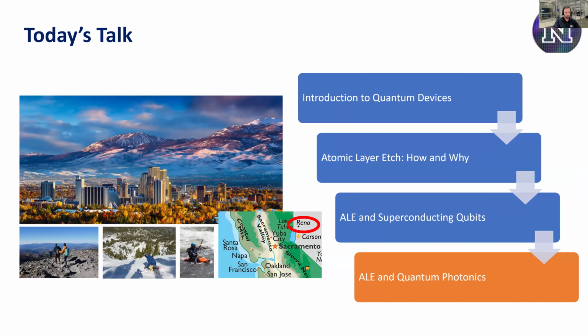The other thing you'll need is to detect the photons at the end, and that's done using superconducting nanowire single photon detectors. These are pretty interesting. You make really thin, like 5 to 10 nanometer thick, superconducting films on a mirror stack. Typically you'll put a little bit of current into the superconducting nanowire. When it absorbs a photon, if enough energy is absorbed, it kicks the wire above its critical current, which breaks the superconductivity, and you see a voltage spike. So they're really just looking for these voltage spikes, but they have to be able to control these things and make these films really, really thin, which is very challenging. They have a lot of issues with line edge roughness and other things. So there are a lot of specific fab challenges here.